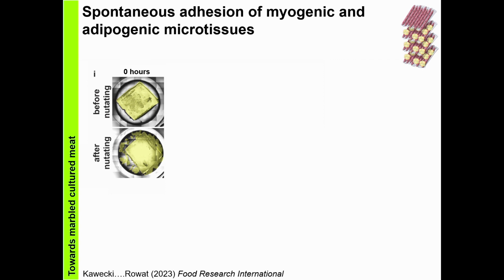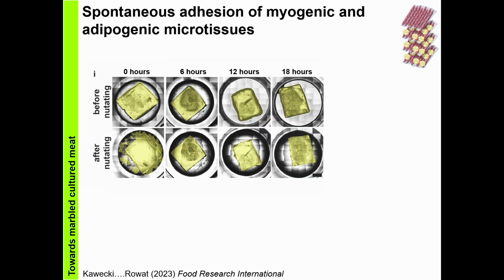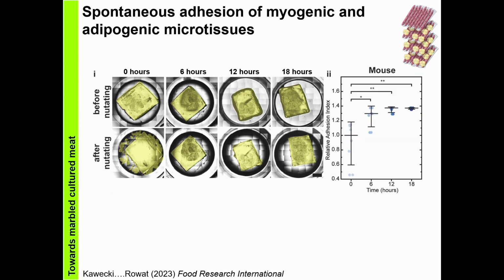microtissue types. But over time, we can see that there's very little displacement at 6 hours, even after 6 hours, or also 12 or 18. So this is showing us that the adipogenic microtissues are adhering, they're sticking to the myogenic microtissue. And we quantified this in terms of a relative adhesion index, building on our image analysis data, to show this relative adhesion index normalized to the median at time 0 for mouse cells on gelatin scaffolds.